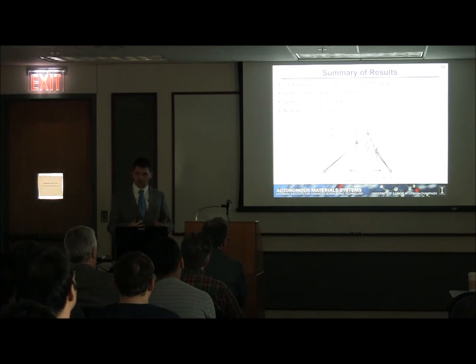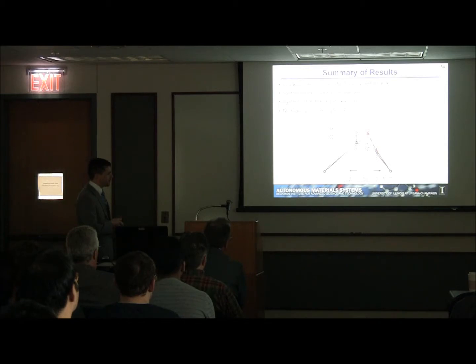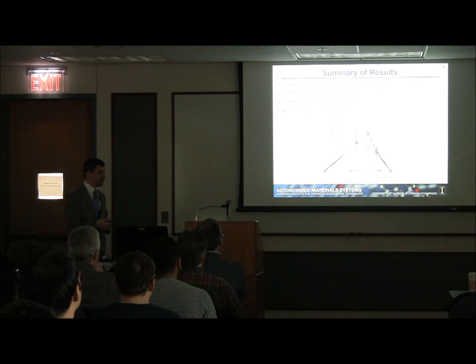So we can plot all those results on the same curve to get a feel for how this works. Here we're plotting the percent resin delivered. Here, 65% resin and 35% hardener delivered is the stoichiometric mix ratio by volume. And then we can plot that using the healing efficiency metric, which I described before. And we see that with the longest pulse duration, the 30-second pulse duration, with the stoichiometric mix, we have roughly 95% recovery of these samples.